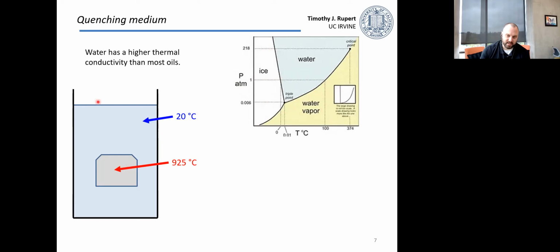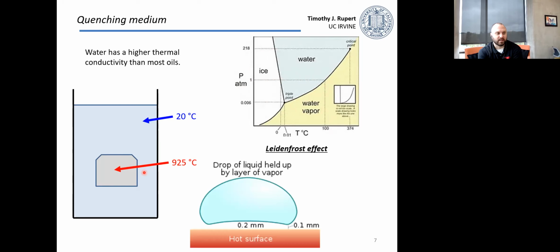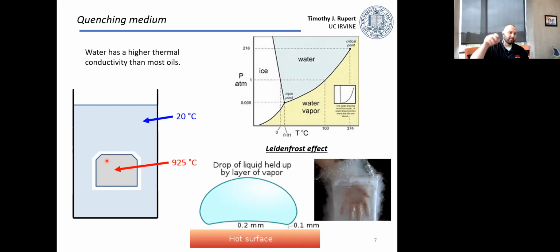The reason that matters is that this sample with a much higher temperature can result in something called the Leidenfrost effect. So the basic idea is if you have a very, very hot surface and you put a droplet of any liquid, but in this case, it could be water near it, that piece of the liquid that's touching that hot surface can very rapidly heat up, and it can go over that temperature at which the evaporation happens. So what can happen is you end up getting a barrier layer of water vapor that separates that hot solid surface and that liquid droplet, okay? So what really happens is if I just put in my really hot piece of metal, I'll actually get something where I have this insulating layer of the water vapor surrounding my metal, okay? That by itself isn't that bad, but if we remember that we want to rapidly cool this down, that can delay things.